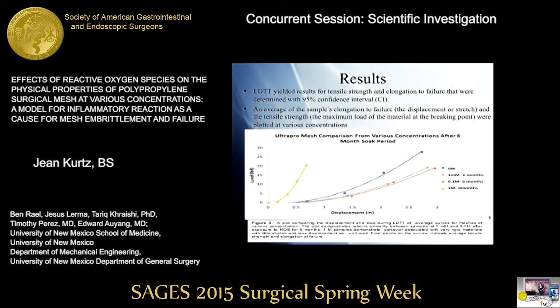They typically were failing at a load around something like 27.5 pounds. They're also significantly stretchy, considering these were 3.5-inch samples in the middle to begin with. They'll stretch over 2.5 inches before they actually snap.